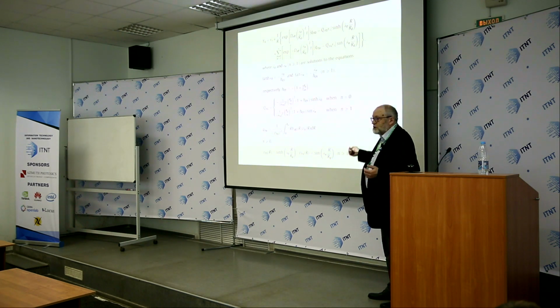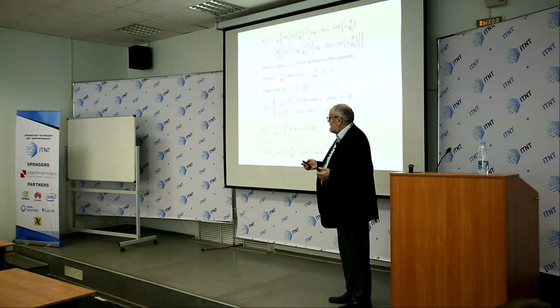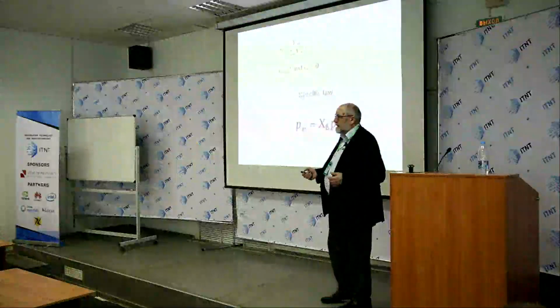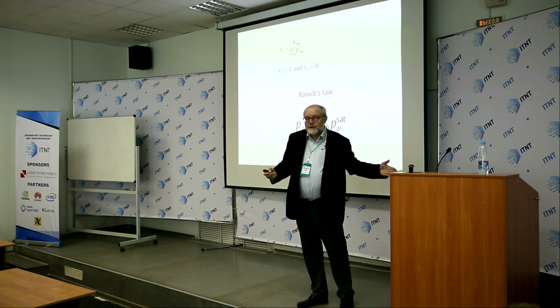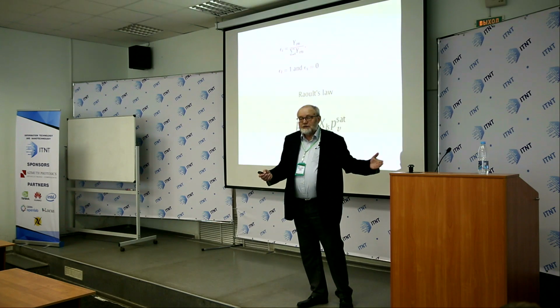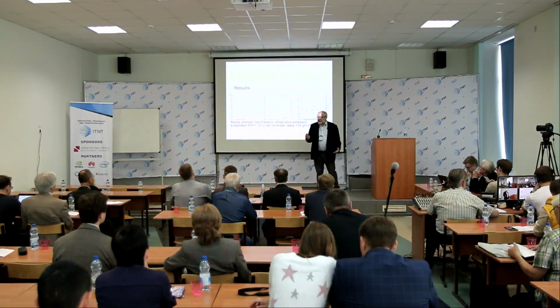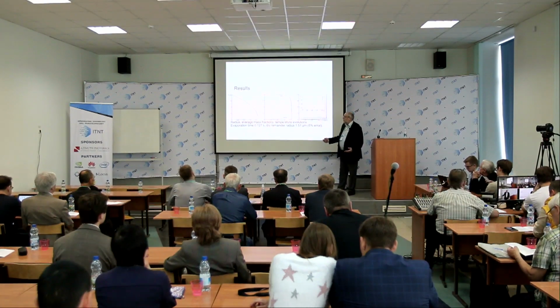I'm not going to show the details because it would be a bit irrelevant for the main message of my presentation. So at the boundary, we assume that the water is the only evaporating substance, and chitosan is not evaporating at all. And then we use the so-called Raoult's law at the surface for the evaporating water. And then, once we have solved this problem, we can get the time evolution of droplet radii and the time evolution of mass fraction of water and mass fraction of chitosan.